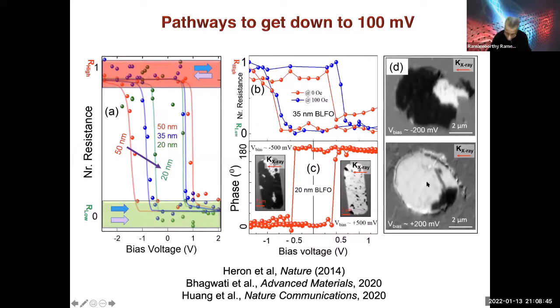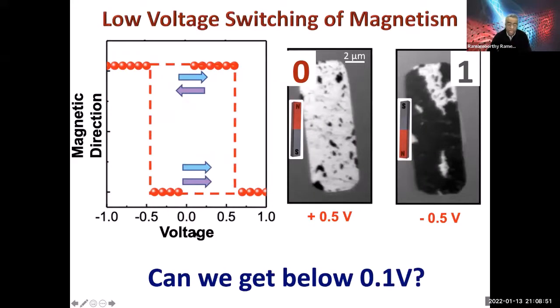So this is still an opportunity. How does one do careful measurements at these kinds of scales? This is kind of an intermediate summary. We now know that we can switch a ferromagnet at room temperature with an electric potential of 500 millivolts. And this is the corresponding PEEM data showing that it's going from magnetized in one direction, up to down. The question is, how does one get below 100 millivolts? That's what Intel is asking for.